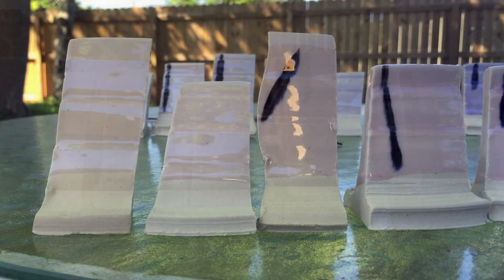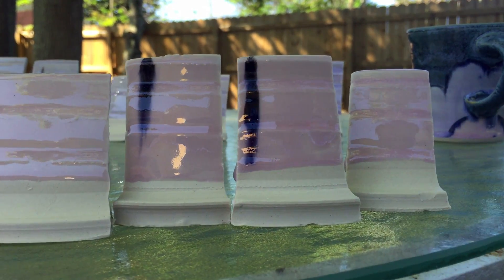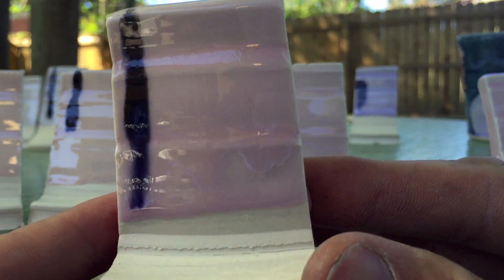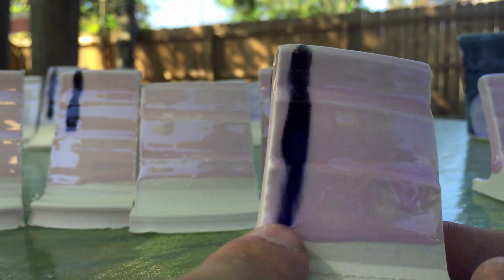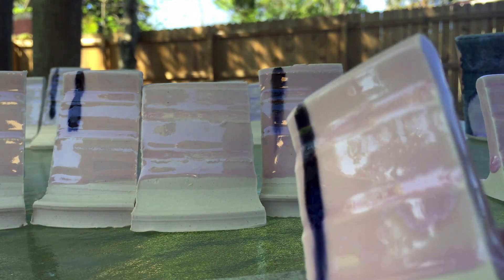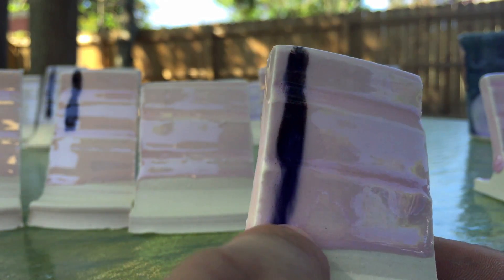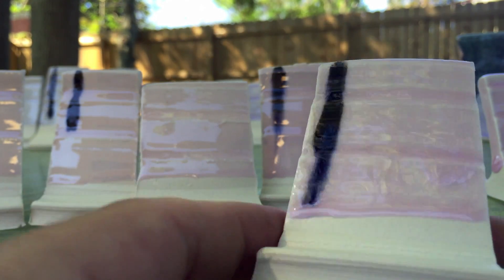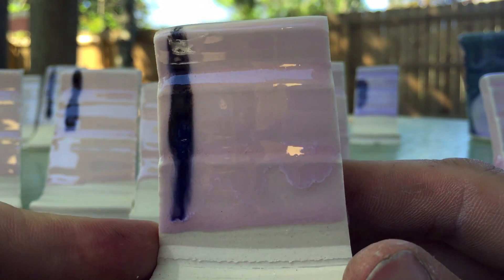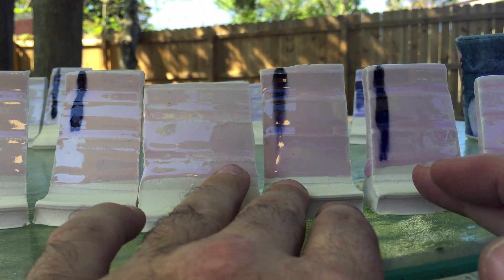Next, let's look at the Erbium. Same thing — we have 1%, 2%, 3%, 4%, 5%, 6%, 7%, 8%, and finally 9% of Erbium. Really happy here. You can see if you look up close there are almost some little white crystals growing in there, but look what it did with that LUG 1 underglaze — it's just gorgeous the way that streaks into the glaze. One of the really cool things about Erbium is that you can get a pink that's transparent. If you used a mason stain like a 6020, you might get the same color but there's no way you'd see the underglaze through it so well. I think somewhere in the 7-8-9% range is what I would use in a glaze.